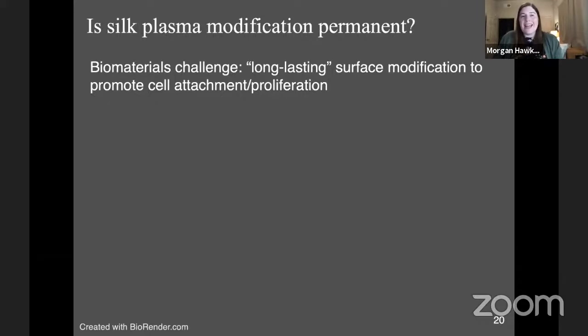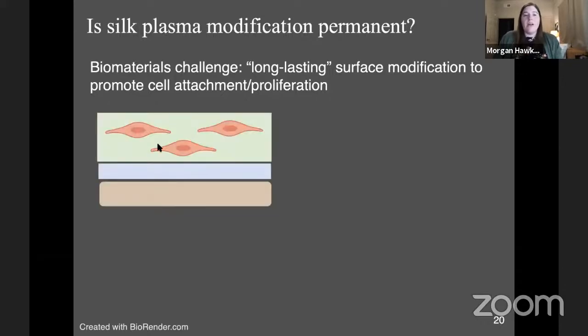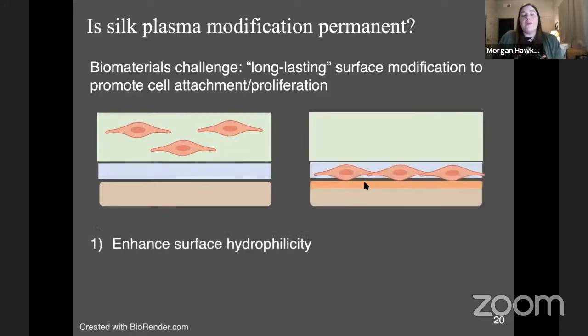So our initial plan was to enhance the hydrophilicity of the silk materials using a water vapor precursor. So here I'm showing an unmodified silk construct with that interface and the biological species, or the biological environment. And our thought was, by enhancing the surface hydrophilicity, we could encourage cell attachment and proliferation on the surface of the material. And my student created a method to use a water vapor plasma precursor. And this method has actually been used in literature to apply to synthetic polymers to functionalize their surface with OH groups, but it hasn't really been used before to modify naturally derived materials, including silk.